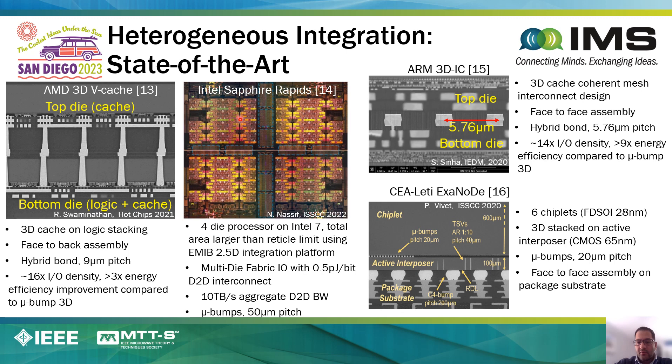In this case, the pitch of the through-silicon vias and the bonds is approximately 9 microns, which is an incredibly aggressive dimension by today's state-of-the-art. This is an example from Intel, where they have taken four CPUs that have been glued together using the EMIB technology, in which there is a little bridge-chip device placed within the organic package that creates high-density connectivity between the four CPU chiplets, making them behave as if they're almost monolithically integrated.